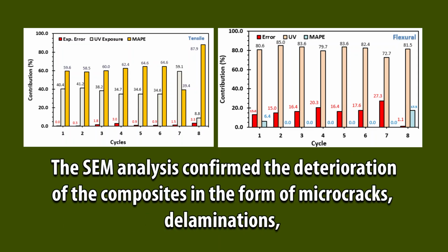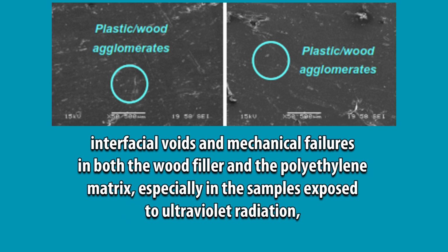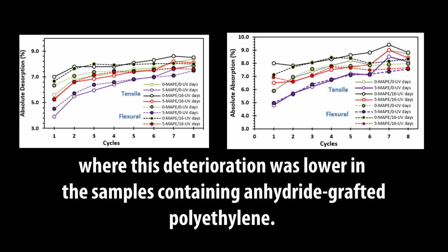The SEM analysis confirmed the deterioration of the composites in the form of microcracks, delaminations, interfacial voids and mechanical failures in both the wood filler and the polyethylene matrix, especially in the samples exposed to ultraviolet radiation, where this deterioration was lower in the samples containing anhydride grafted polyethylene.